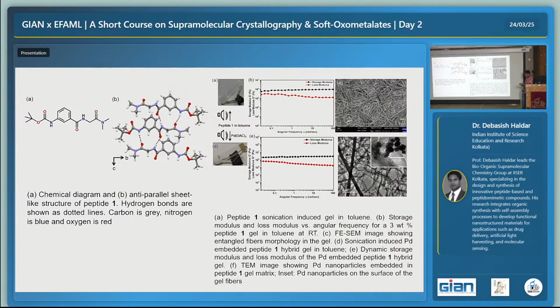From X-ray crystallography, again this compound forms an anti-parallel beta sheet-like structure, and finally it forms the fiber, it forms gel in organic solvent. During gel formation in toluene, if we use palladium acetate, the palladium acetate will interact with the N,N-dimethylamine and convert to palladium 0, to palladium nanocrystals, and those palladium nanocrystals will be covered with the gel surface.